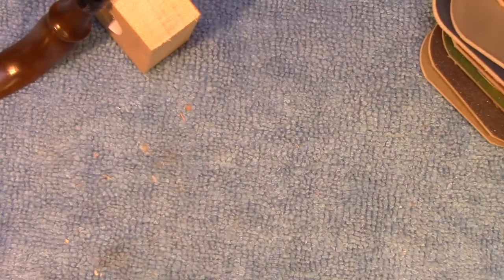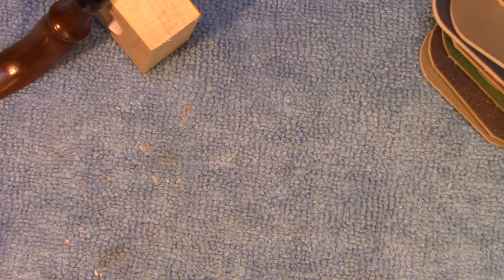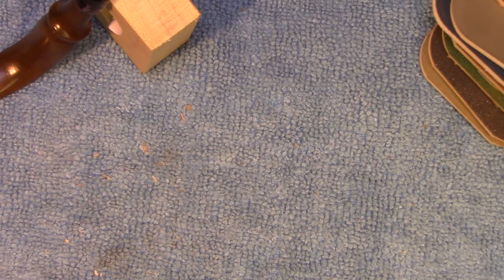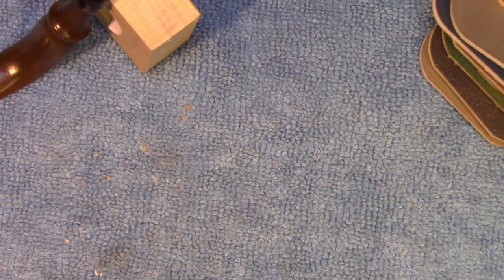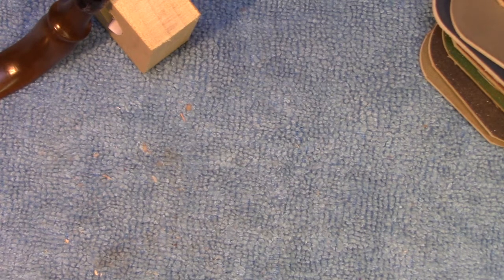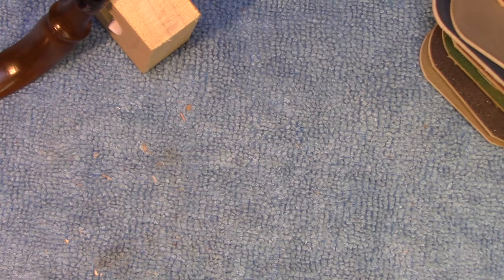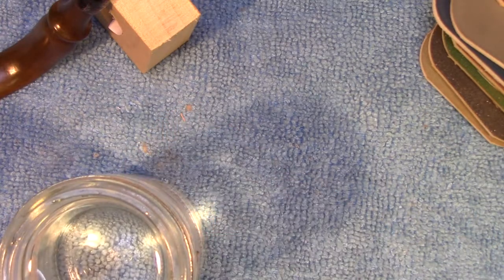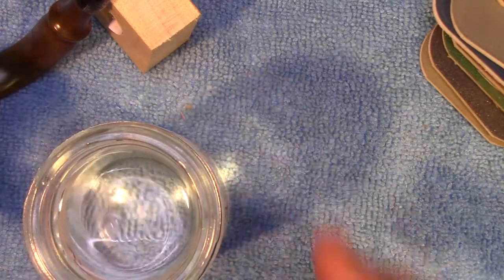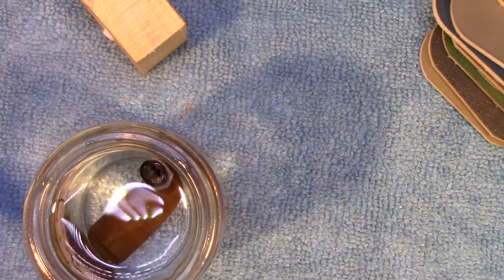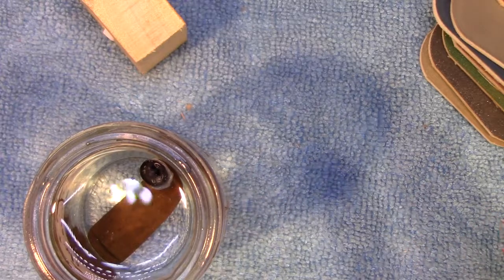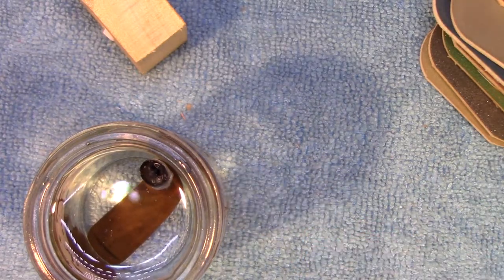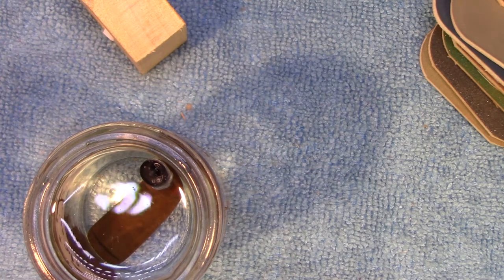This is essentially a 3% solution of hydrogen peroxide in hot water. And we will just insert the stem into that solution and let that soak in there for a few hours, maybe two hours.